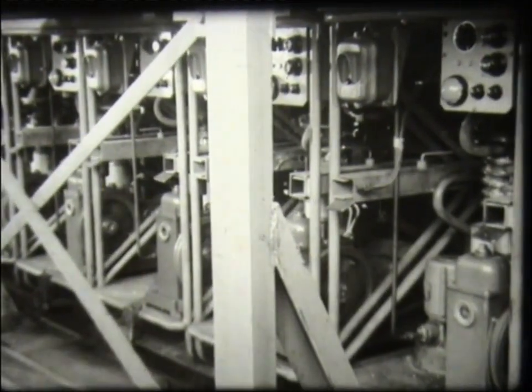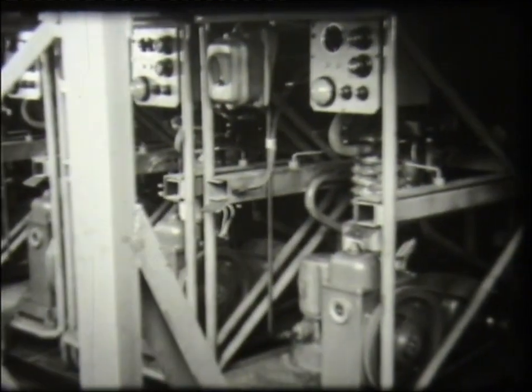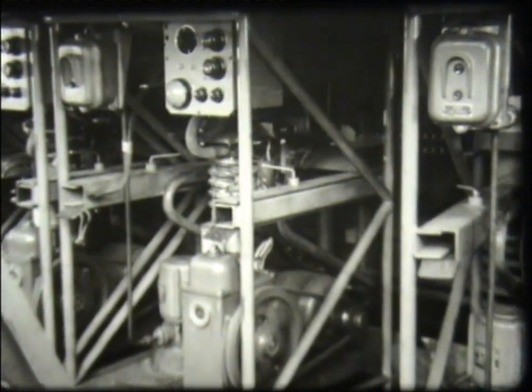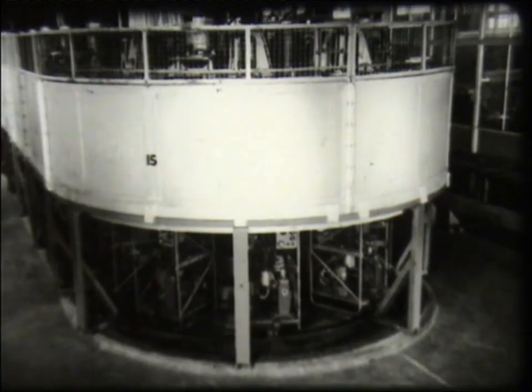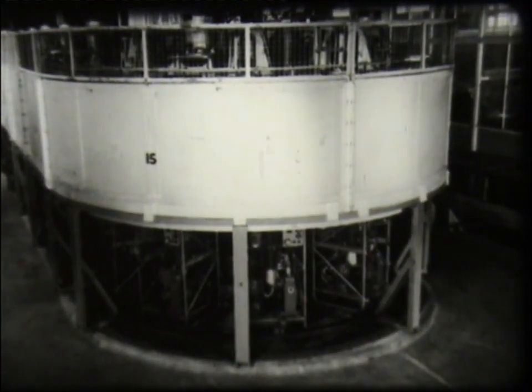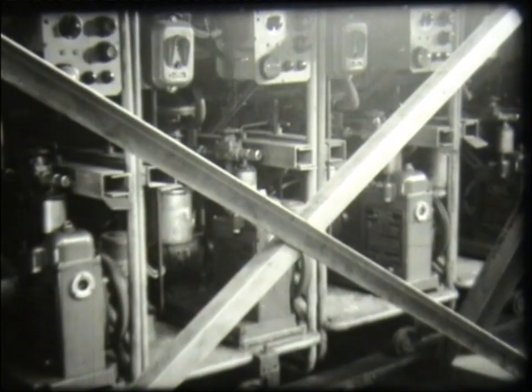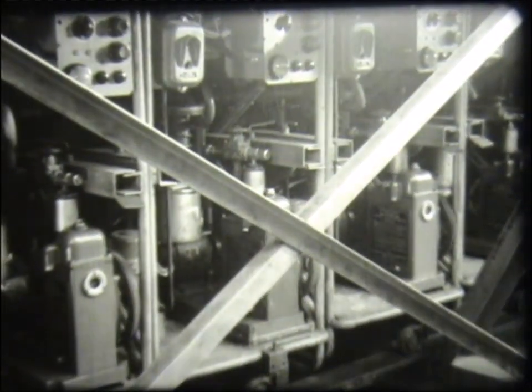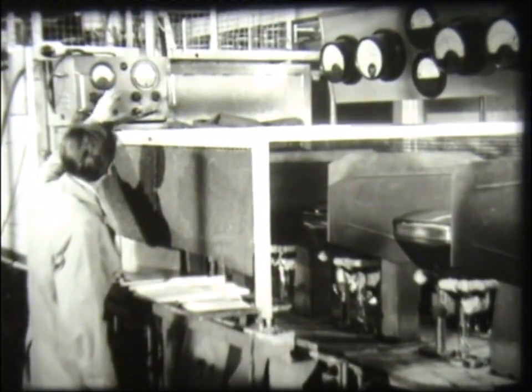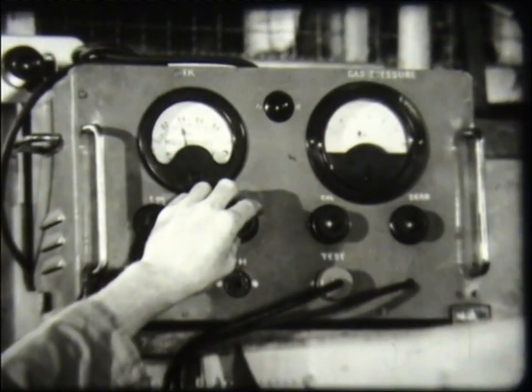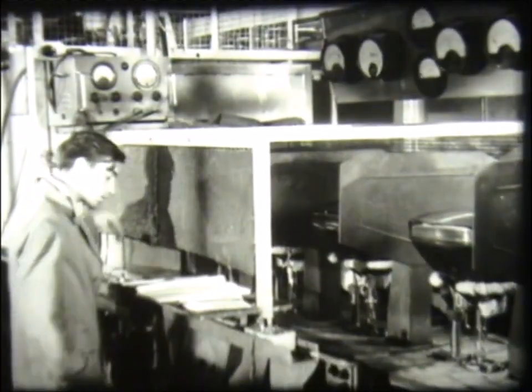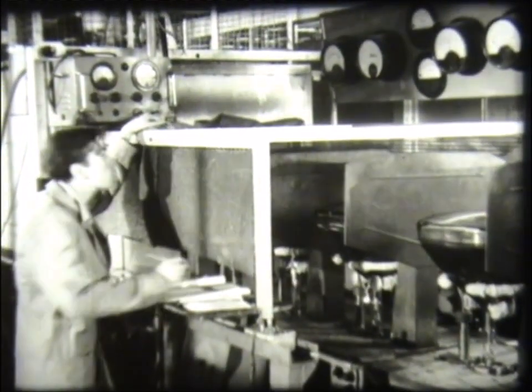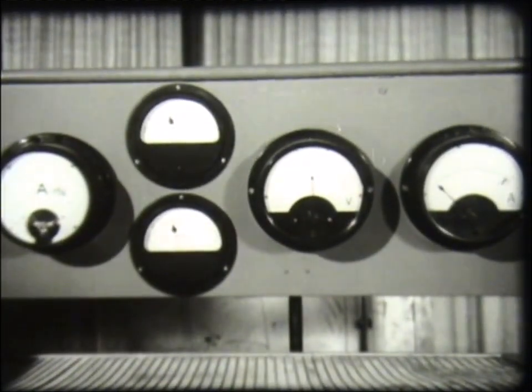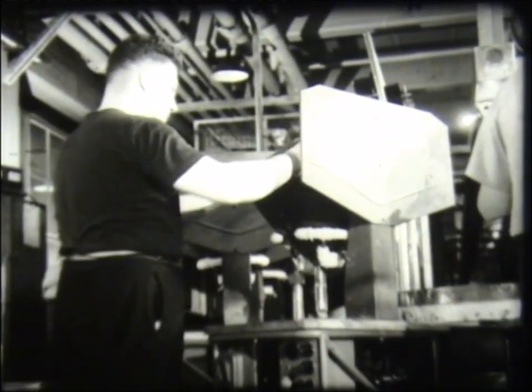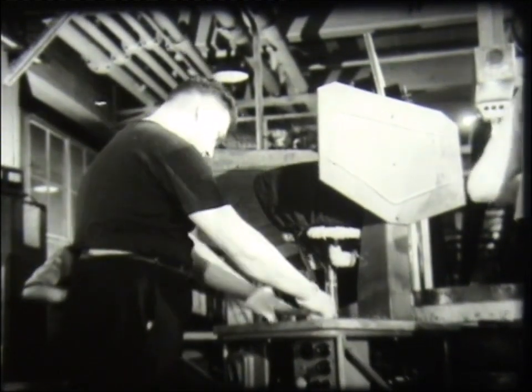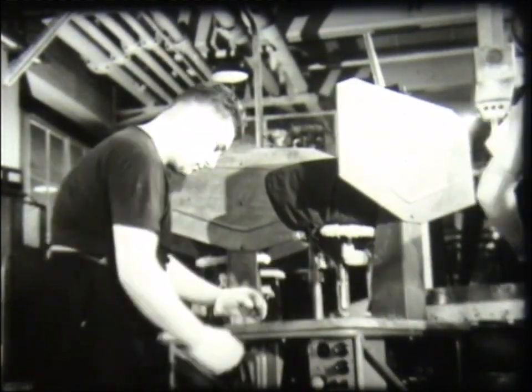This causes chemical changes in the emissive coating on the cathode, the original coating of barium and strontium carbonates being reduced to barium and strontium compounds having emissive properties. On emerging from the pumping plant, the degree of vacuum is checked by measuring the ionization current through the tube. Finally, heat is applied to soften the pumping stem so that the tube is automatically sealed off.